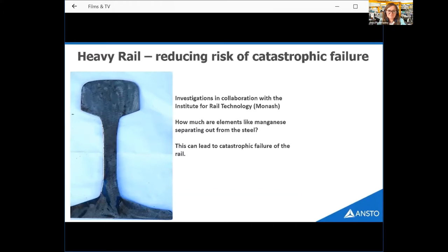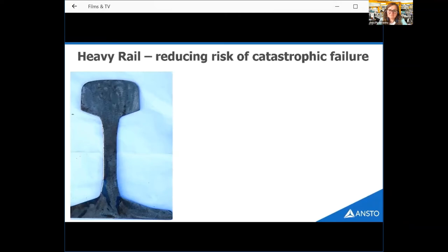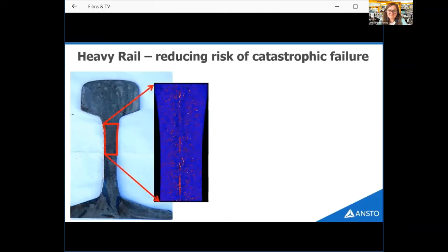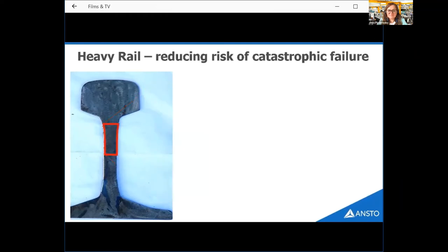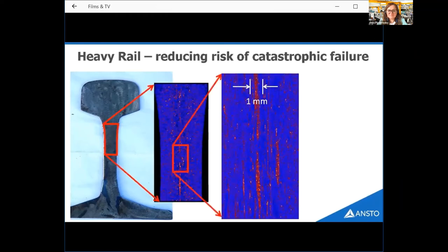So in this past partnership, the synchrotron was used to investigate how the uneven distribution of elements such as manganese affects the reliability of welded rails. So we're able to map this entire section of rail. If we look at this load-bearing section, we can visualize manganese distribution with hotter, more red colors, meaning higher concentration of manganese. Here we can see some linearity, but if we zoom in, we can actually measure the distribution of these regions and the extent of separation. And this all feeds into steelmaking and design to improve the lifespan and the performance of critical railways and enable better prediction of potential failures.